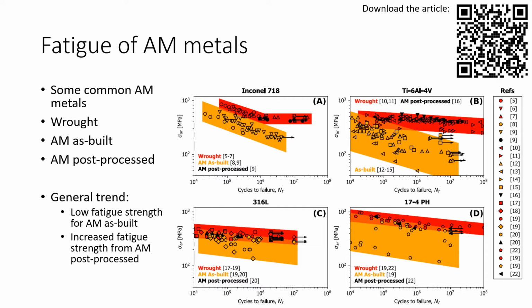This is some data of common engineering materials produced by additive manufacturing and conventional methods, wrought, and it's Inconel, Ti64, 316L and 17-4PH stainless steels. And we see that the general trend is that the as-built additively manufactured specimens are having reduced fatigue strength, while if we see the black dots, those are post-processed, like for example machined or heat treated. So the fatigue behavior is increased to the same level or even higher than the wrought material.